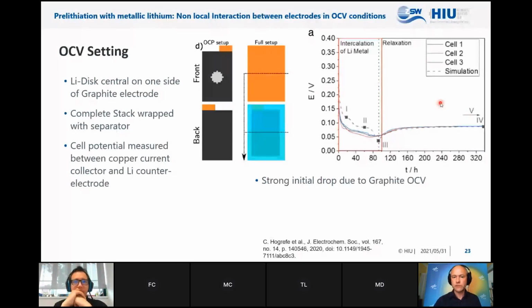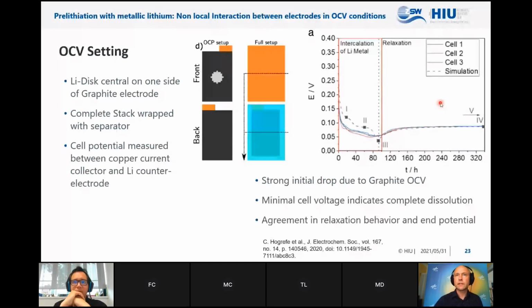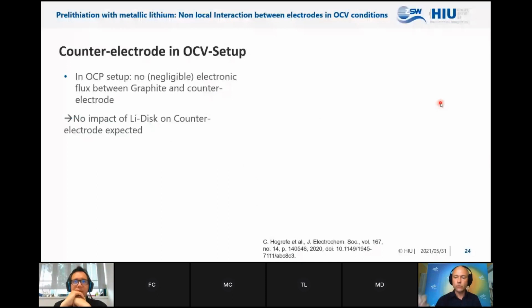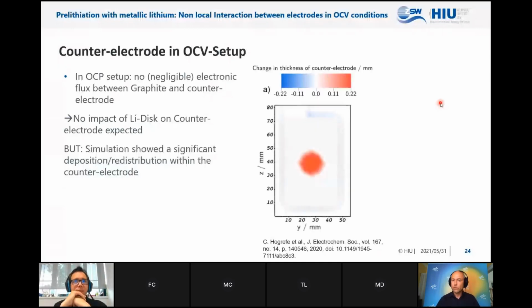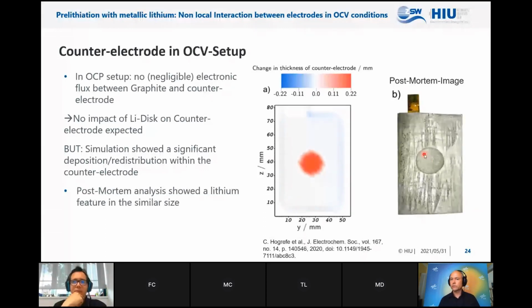So far, this was a very interesting result, but then it became more interesting when we observed what is going to happen with the counter-electrode. Again, I want to remind you there is no external current flowing, so in principle, the lithium on the counter-electrode should not be affected whatsoever. But our simulation showed a very interesting feature, namely that suddenly on the counter-electrode, you found exactly opposite to the disk an enhanced deposition of lithium and a reduction of the lithium on the rest of the counter-electrode, which was exactly observed also in the post-mortem image in the experiment.